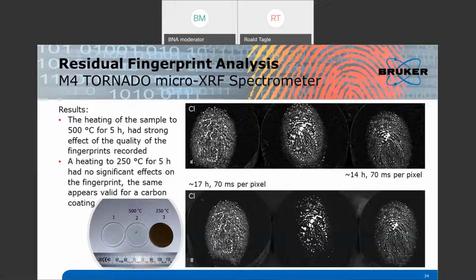And basically, we are not really experts in terms of fingerprints, but if you take a look at the images, the measurement time was the same per pixel, just the area is a little bit larger, so that's why one was a little bit longer measurement time than the other. But the acquisition time per pixel is exactly the same in both measurements. And you see here that especially the sample treated to 500 degrees is very strongly affected. The image quality, you can see it's a fingerprint, you can identify some of the structures, but it is really a very strong decay of the fingerprint quality. In the case of the 250, we were not really seeing any significant changes in the fingerprint quality, neither by the heating nor after the coating.